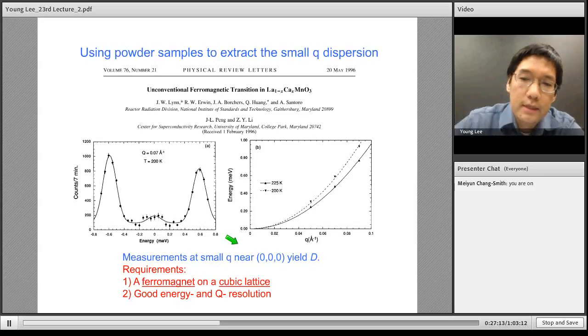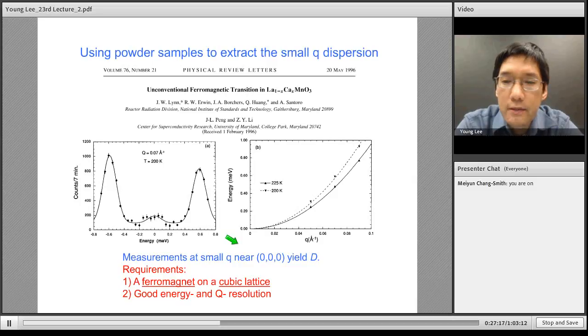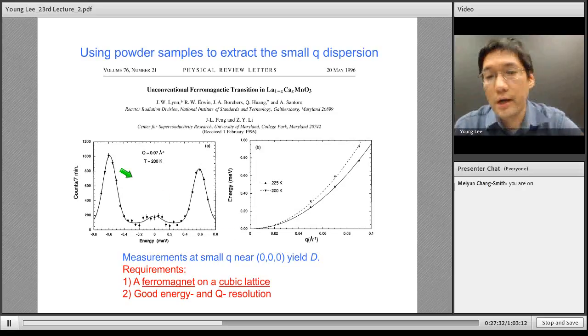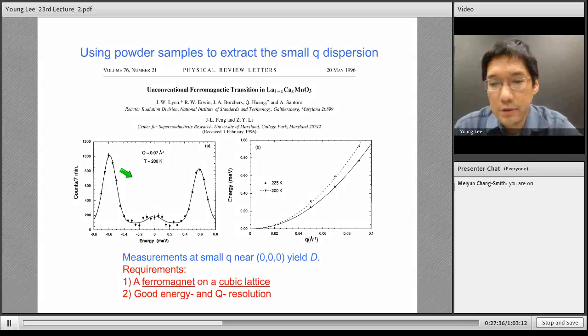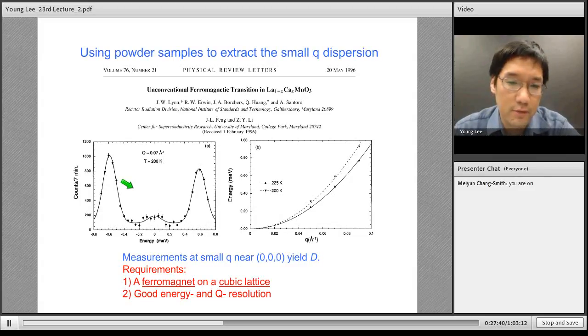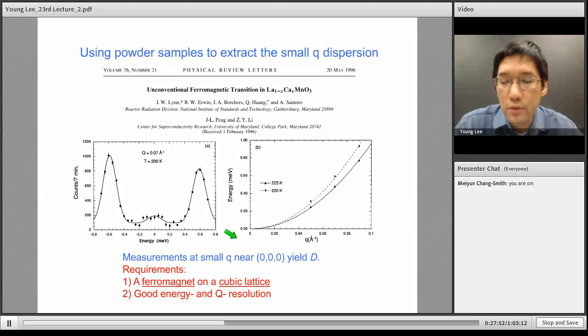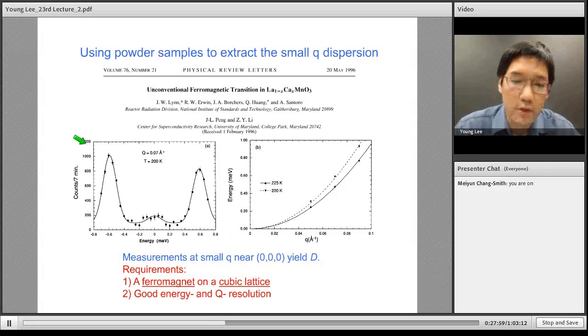Now you can imagine that for a powder sample, if you were at large Q and looking at Brillouin zones away from Q equals 0, then you'll be mixing up zone centers with other zone boundary positions, and what you would measure if you scan energy would be some broad collection of excitations because you're measuring several Q positions simultaneously that have different energies for the spin waves. But near 0, 0, 0 for a cubic system, the dispersion is isotropic. So even if you average over different orientations, they're still at some fixed Q away from 0, and they will all have the same dispersion, this quadratic dispersion from the 0, 0, 0 position.